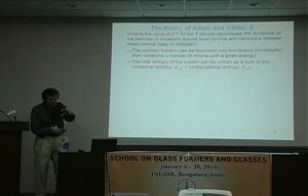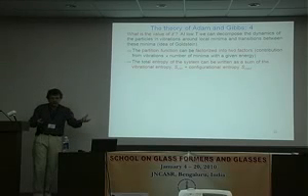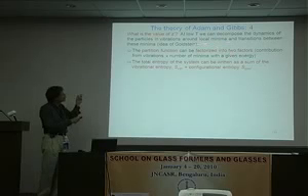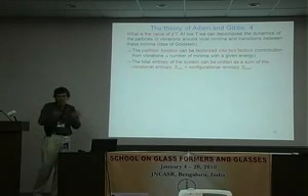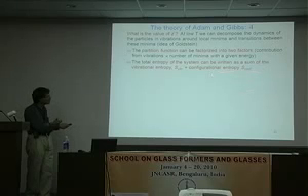Okay. Now, we try to understand what is the value of Z star, that is to say, the minimum size of a cooperative rearranging region that is able to do something. We have seen yesterday that at low temperature, you can decompose the dynamics into fast degrees of freedom and slow degrees of freedom. That is to say, you have vibrational motion and relaxation. This is the idea of Goldstein: you have a minimum around which the system vibrates. Therefore the partition function can be factorized into two factors: the statistical mechanics that comes from the vibration and the statistical mechanics that comes from these various minima. And therefore, the total entropy of the system can be written as a sum of the vibrational entropy and the configurational entropy. The vibration is just harmonic oscillators, and the configurational entropy takes into account how many minima you have at a given temperature.